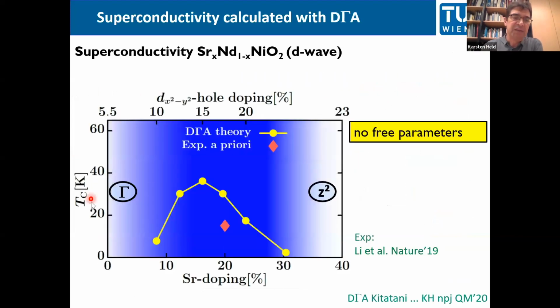So that is TC as a function of strontium doping. As I've explained before, you have to translate it into the actual hole doping of the x squared minus y squared orbital. And it's a non-linear scale, as you see here. That will become important. At the time of our calculations, there was this single experimental data point available, and that is the calculated TC. So we didn't adjust any parameters. We did the best we could do.